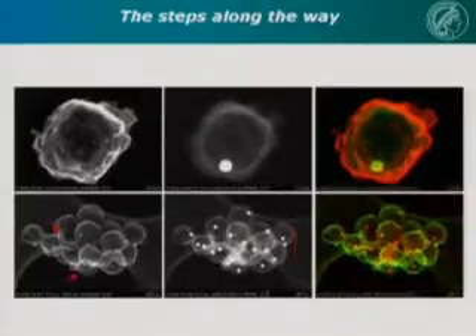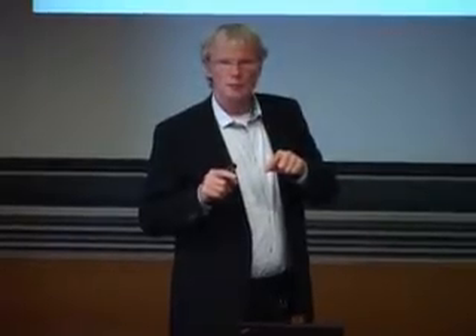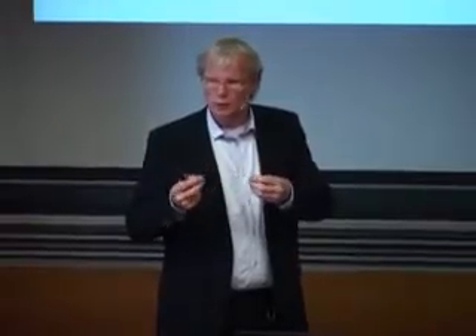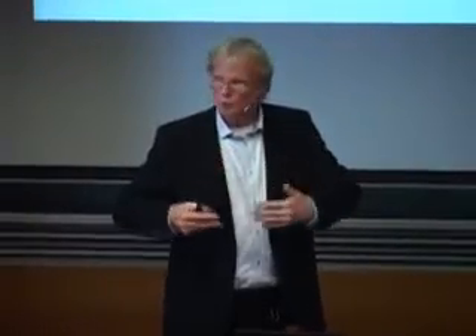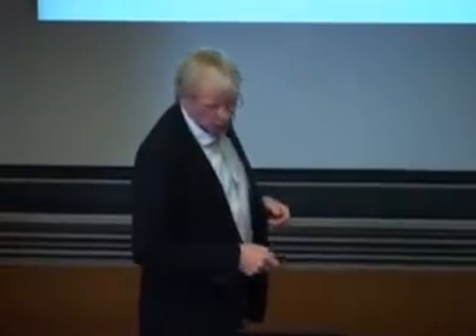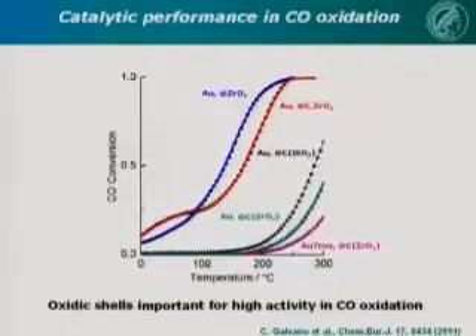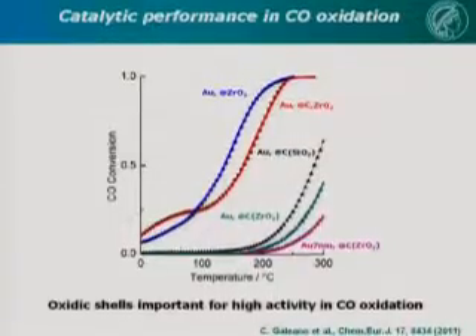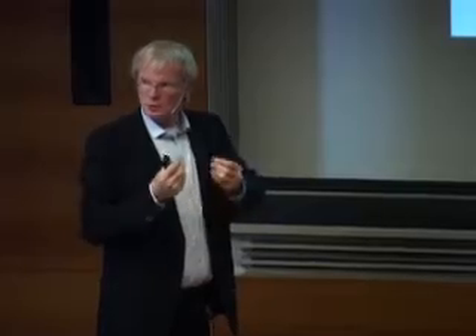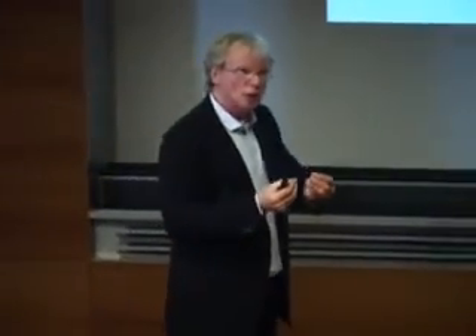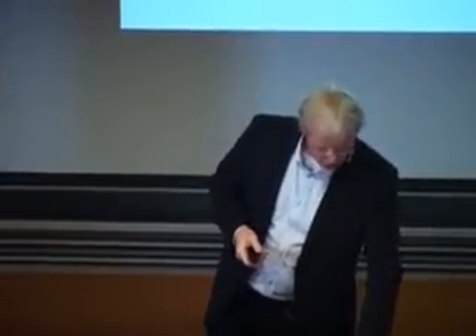And now comes the interesting question: are the catalysts still active when they are in carbon? Because in gold catalysis, CO oxidation, there is always the notion you need an oxidic support. You need oxygen from the support to assist in the gold catalysis. And lo and behold, as long as there is oxygen in the shell, either here gold in zirconia or gold in the carbon-zirconia composite, activity is high. As soon as you leached, and in the brackets I just indicate what is leached out, it's not present anymore. This is really gold in carbon made from the porous silica, gold in carbon made from the porous zirconia. These are smaller gold particles. Activity is strongly reduced. So a good oxide is actually very beneficial for high activity in CO oxidation.